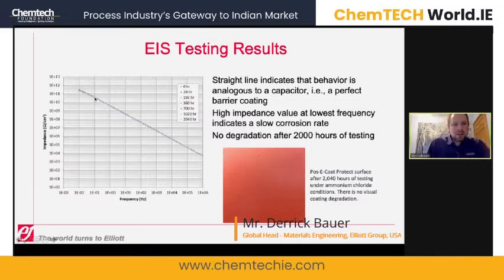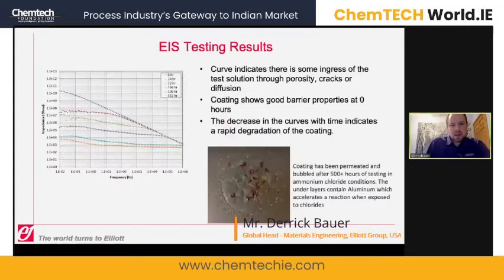So what is shown here in this graph on the left is the impedance, the capacitance resistance over a 2,000 hour time period. There's actually 7 or 8 lines all on top of each other here that showed that even from the initial start of the test through 2,000 hours, there was no change in the corrosion behavior of the sample. Essentially, the coating remained intact after 2,000 hours. An example of a coating that did not work is shown here, where you could see at 0 hours, there's a good capacitance. However, over time, this capacitance degraded as the solution had diffused through the coating and caused corrosion.